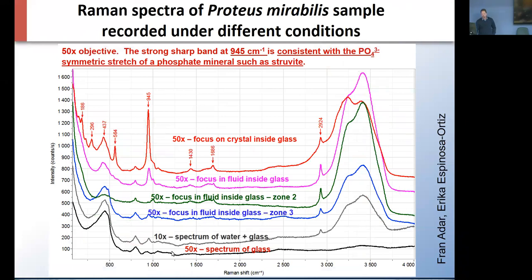So what we then did is we looked at different parts of the capillary. The glass, the water, close to the glass, some of the liquid inside the glass, and then closer and closer to the crystal, we started seeing this peak here, as well as a few other peaks. But this peak was of specific interest to us because the 945 is an indicator of a symmetric stretch in phosphate. So this indicates that it's struvite to us. It isn't a final proof, but together with the SEM analysis afterwards, as well as XRD, we can then conclude, yes, this is struvite. But this was non-destructive, and we could do this over time.